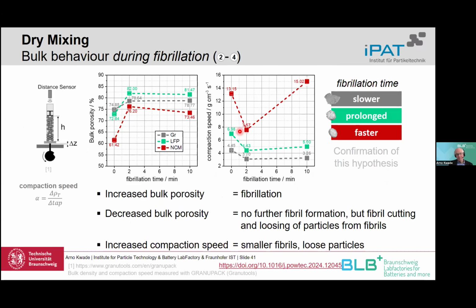What happens now with the properties of our powder, and you see, for example, the bulk porosity first increases after fibrillation because you get agglomerates. You can think about that, and after further fibrillation, it changes a little bit, maybe decreases slightly, but there's no big change anymore. In the compaction speed of such a tapped density measurement, you see that after fibrillation, because we have this high porosity, the compaction speed increases a lot, but then decreases a lot because it is more fluffy, and after we have more fibrillation, it stays almost the same, or in the case of NMC, it increases again.